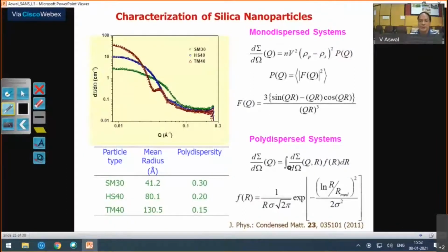And for that you use a log normal distribution, because a normal distribution cannot account for the larger sizes of the particle. If you fit a symmetric distribution like a normal distribution, then it is not possible because of the very large sizes. But if you use a kind of distribution which can have a long tail, then it is the correct distribution to fit the large sizes of the nanoparticles. Along with this, the others have higher polydispersity and you don't see the oscillations. Okay. This is much larger than the other two. So the scattering intensity is larger and the width is also.